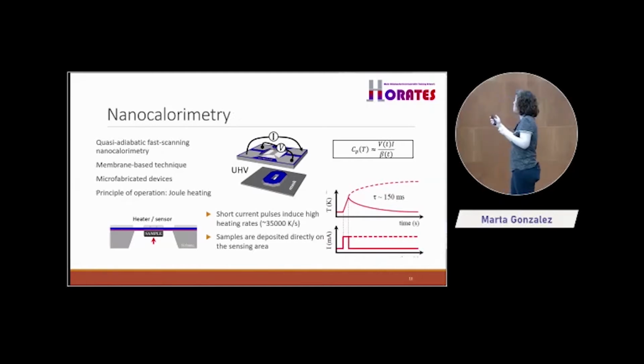And this platinum circuit is acting both as a heater. You remember that we needed a heater to provide power and heat the sample. So it's working both as a heater and as a sensor. The heater, because what we can do is connect this, this is a 4-wire configuration. We connect this and provide a certain intensity that we know, okay? This intensity will heat up our platinum by Joule effect. So that's it, we have it, okay?